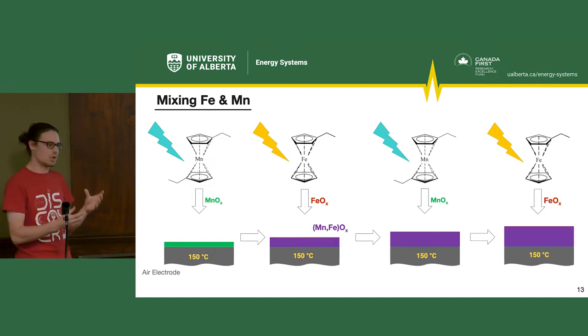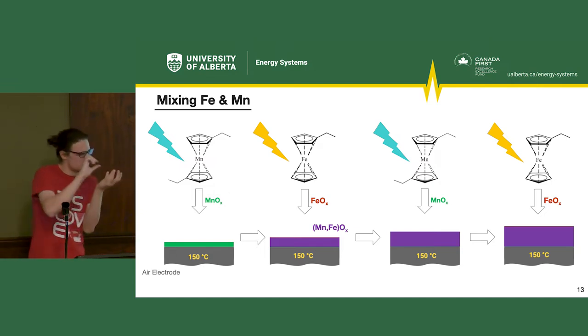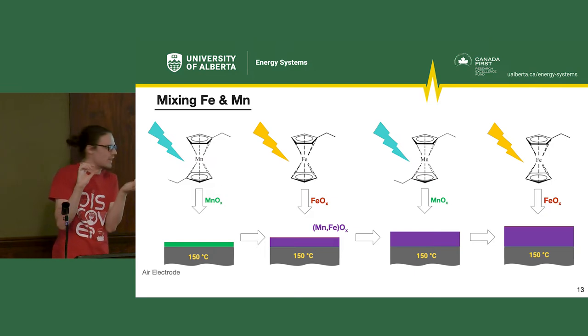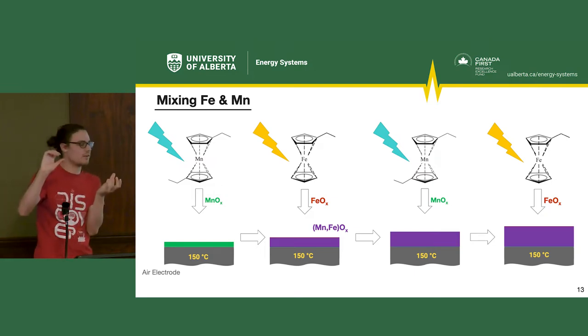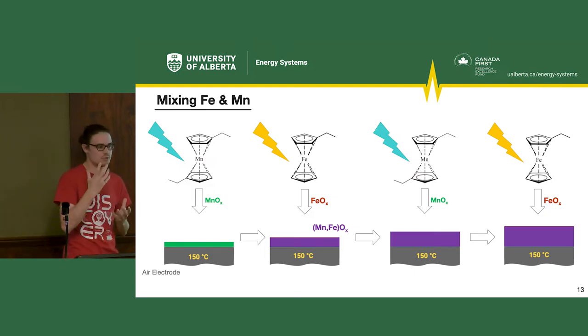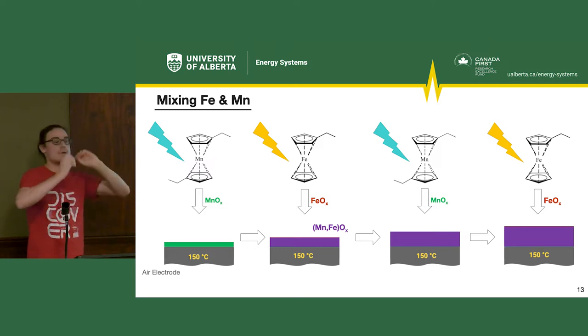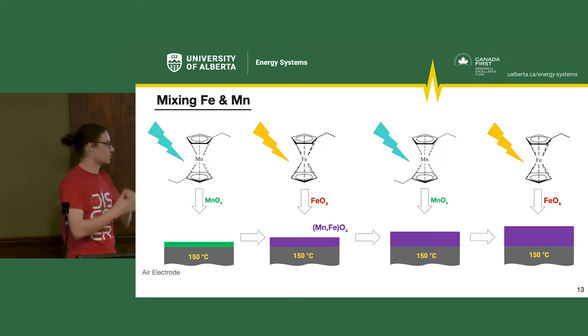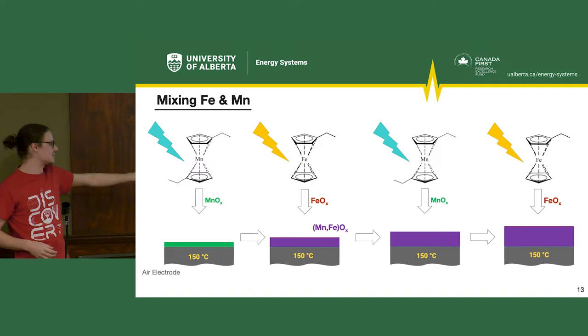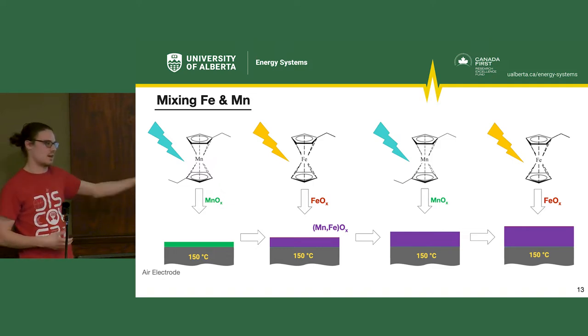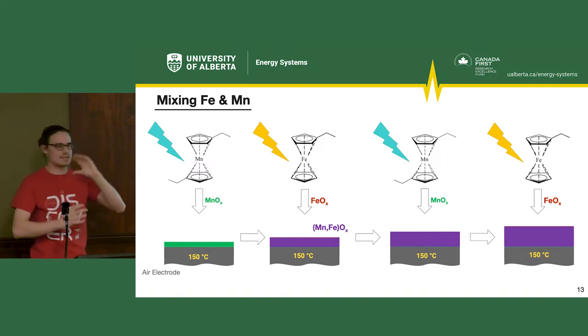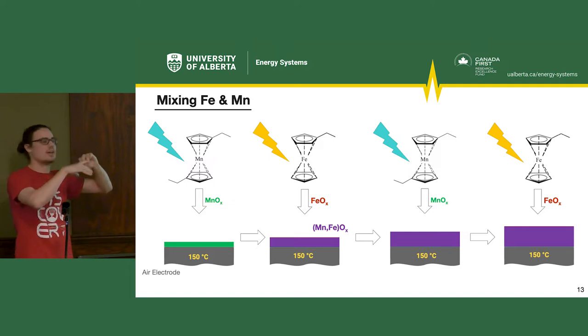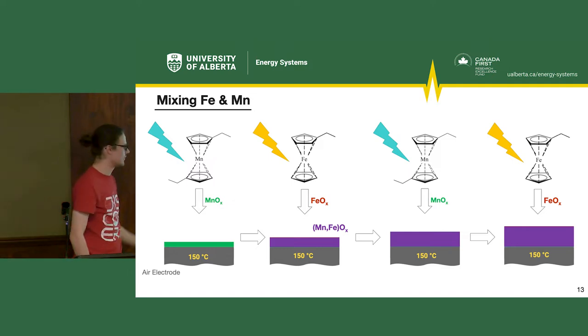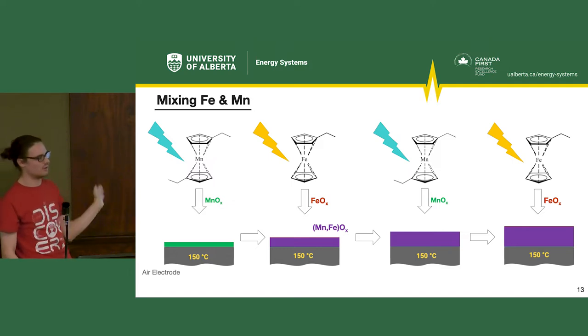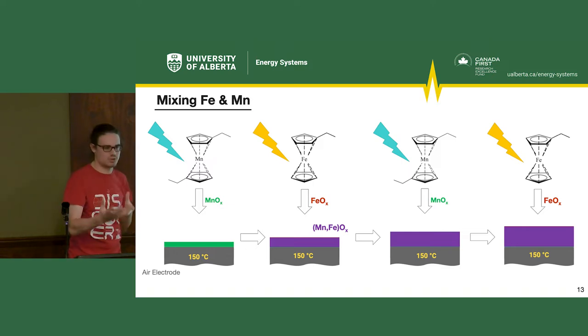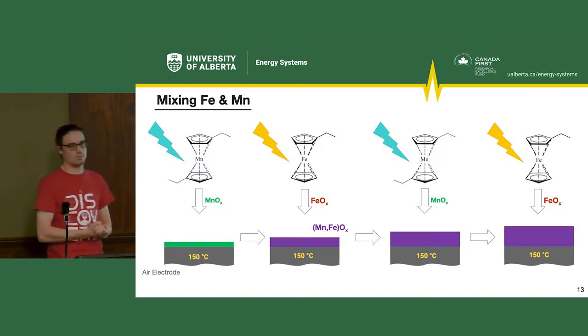And as a result, when I'm depositing, I deposit maybe like 10 atomic layers of manganese, and then I do 10 atomic layers of iron. And because it's elevated temperature, and these are atomic layers, they're going to start mixing as I deposit it. So I'm going to start getting a mixed oxide, a mixed manganese iron oxide. And the two of them can kind of intermix, and it's not one or the other, like layers. It's a complete mixture. And then I repeat the manganese, repeat the iron, repeat the manganese, do the chemistry that's the best ratio for what I want.